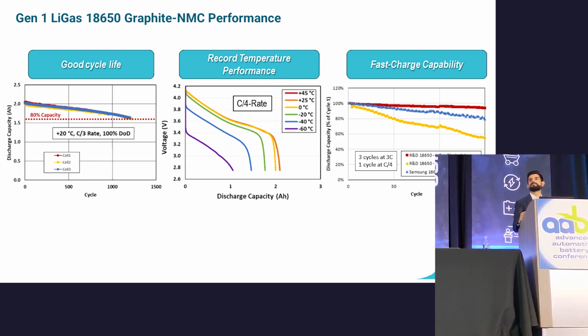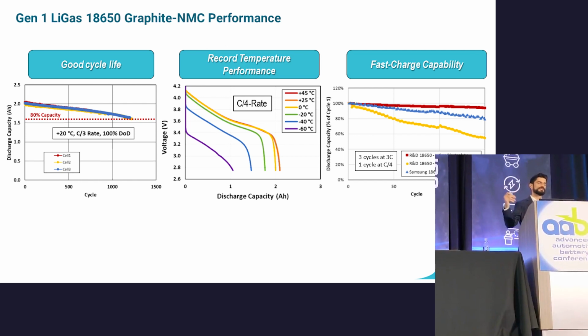I also highlighted our record low temperature performance. We go all the way down to -60, still cranking out about 40 or 50% discharge capacity. Nobody comes close on this one. We also operate up to 60 degrees Celsius with very good discharge performance as well.